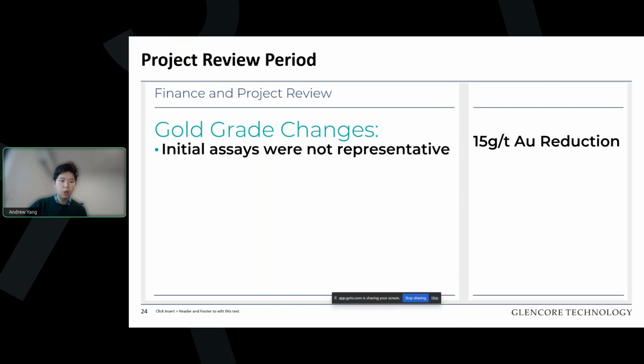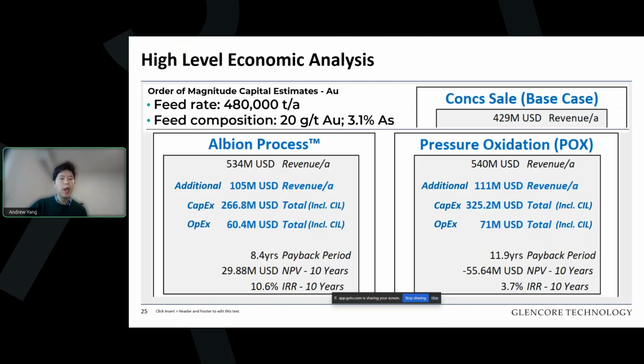With a drop in the gold grade to 20 grams per ton in concentrate, our revenue is going to drop, so our base case is going to drop. The amount of additional revenue is also going to drop as well, but the CAPEX and OPEX is going to remain the same. And then we can see here that the payback period starts to change as well. However, the Albion process is a lot more resilient, I would say, than POX here for this particular scenario. Despite the increase in the payback period and the slightly lower NPV and the change in the IRR, we can see that for pressure oxidation, when we start to drop the gold grade, the NPV starts to go a little bit more negative.